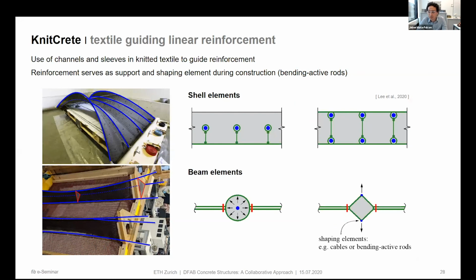And finally, we don't only want to build elements with this textile reinforcement that at the end has a brittle failure, but our ambition is also to integrate features that allow us to integrate some channels for the reinforcement into the structures. And in this way, maybe we can use conventional reinforcing bars that do not have to be pre-bent, and we insert them inside the textile, and then this can be some bending active elements that act as tensioning elements of the textile, but also as a final reinforcement. And I think this also has quite some potential for shell elements and also beam elements.